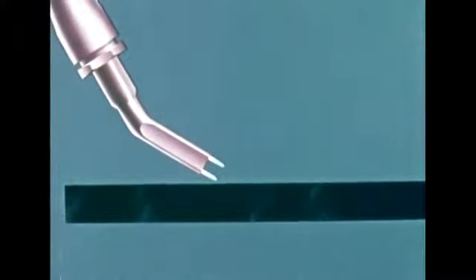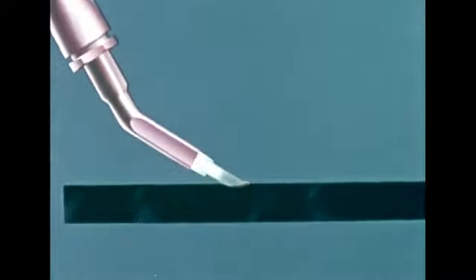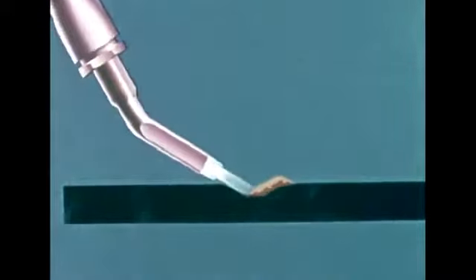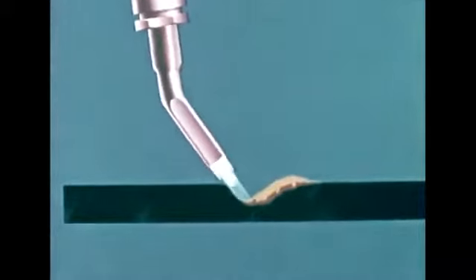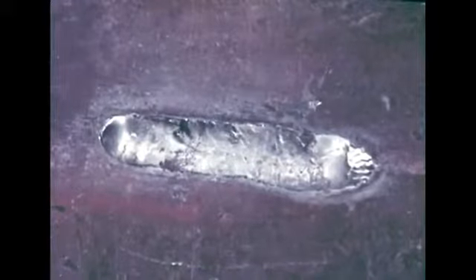Because the nozzle angle is so important, let's watch it again in animation. Preheat with a nozzle at a 30-degree angle. When the metal turns red, press the cutting oxygen lever, draw the nozzle back, and decrease the angle. Then increase the angle to direct the cut downward. Flame gouging leaves a U-shaped groove which needs no additional preparation for welding.